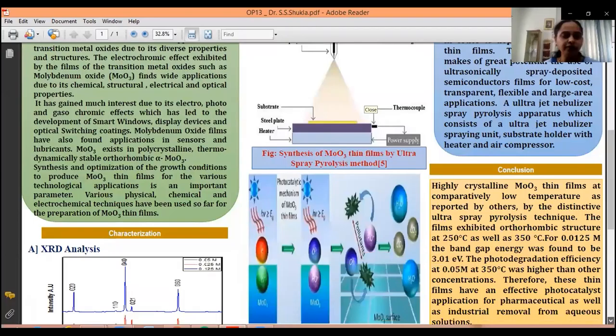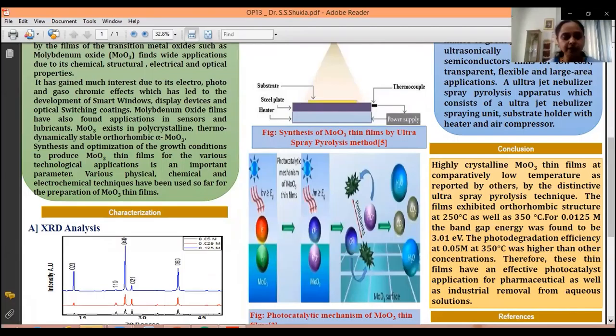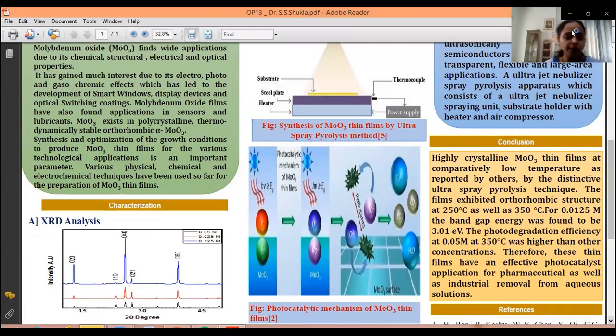The observed XRD patterns were confirmed with the standard JCPDS card file 005-0508. Films obtained were polycrystalline with well-defined peaks along the 020, 040 and 060 planes, as shown in the XRD diagram for 350 degrees centigrade, confirming the alpha phase. The grain size varied from 53 nanometers to 65 nanometers.